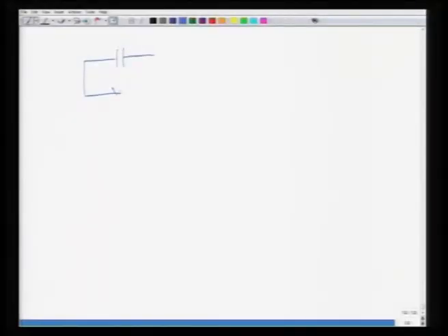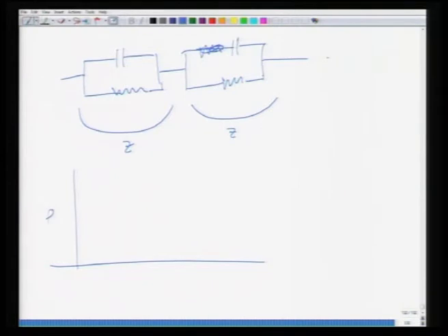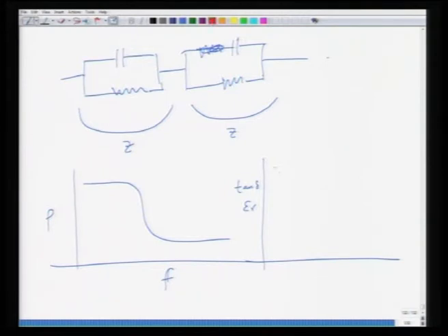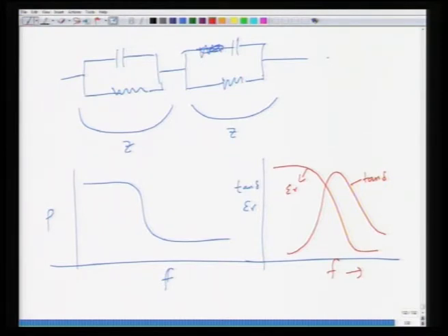Since the grain and grain boundaries are different, you can treat them as shunted capacitors connected in series, just like we saw in dielectrics. Each will have its own impedance. When you plot resistivity it shows a frequency dependence, and similarly you can note the effect when you plot tan δ as well as relative permittivity versus frequency — the permittivity and tan δ both show frequency-dependent behavior. These contributions can be extracted by doing proper analysis of this electrical circuit model.